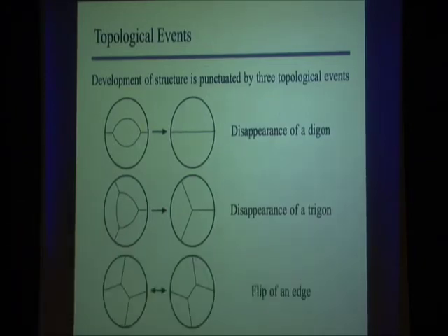So when you say the first one has been found, computationally or in reality? Well, in reality, most of the systems that we look at are three-dimensional, and so we look at two-dimensional sections of these, and you can watch those evolve, but because you're working in 3 dimensions, because you're working with a 3-cell complex, a lot of the rules that I'm telling you don't work. If you look at just an arbitrary section of a 3-cell complex where you have this constraint that the surfaces come together at dihedral angles of 2 pi over 3, depending on the section, that's not satisfied in 2 dimensions. So a lot of what I'm telling you is just not applicable.